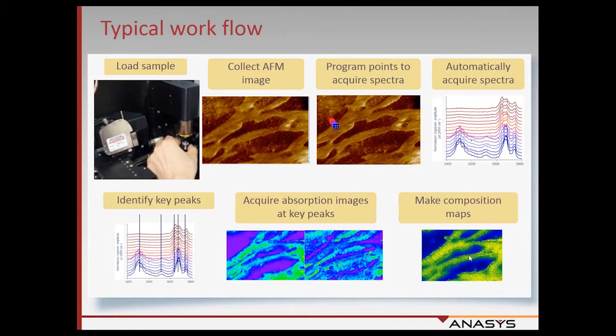All right, so the typical workflow, and Greg will talk more about this, is basically you collect an AFM image, you can program some series of spectra, you can then acquire those spectra automatically, identify the key peaks that distinguish the different materials, and then you can tune the laser to any specific wavelength. We use narrow band laser sources so that you can tune to any absorbing band and then collect an absorption image, and Greg will show you a number of examples of this. And you can make ratiometric images where you compare the ratio of absorption at one peak versus another peak, and then make nanoscale composition maps based on that.